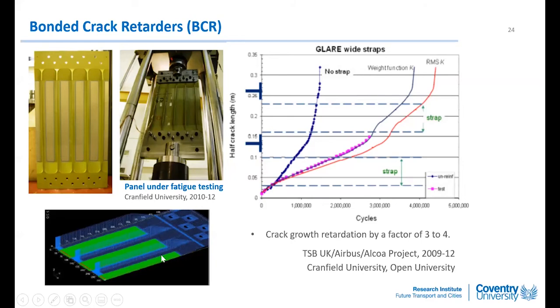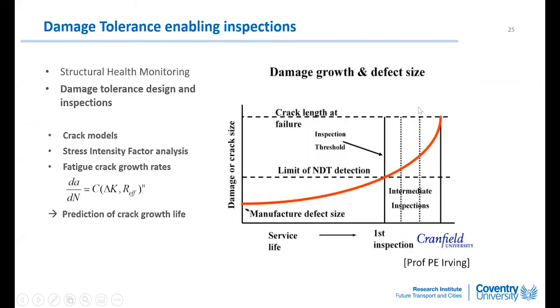We also did the finite element modeling and fracture mechanics analysis, with 2 different calculations of the stress intensity factor, by either weight function or root mean square method, and we get some good predictions. So finally, the reason we calculate the crack length versus fatigue life is because we want to set an inspection regime for the airline operators. So they will have a good time without inspection. That is the crack size before you need to do inspection. And after the first inspection, they schedule intermediate inspections, like every 6 months. And that just makes sure any crack developed will be caught by inspections.